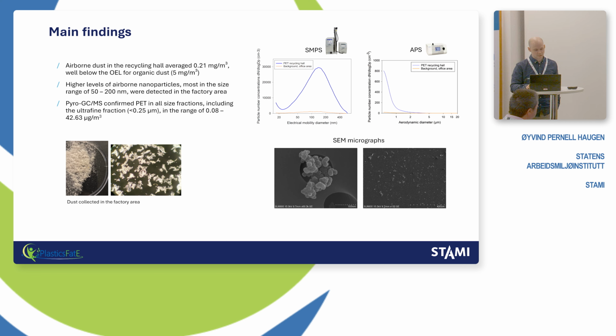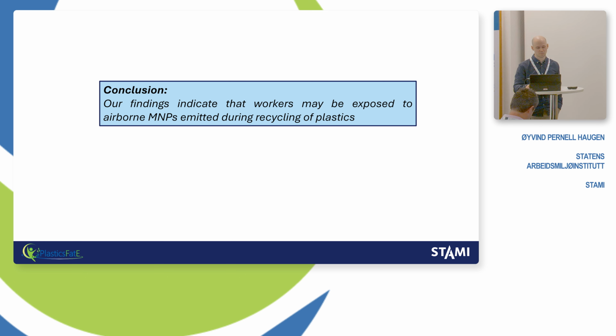And pyrolysis GCMS, I don't have the numbers, it's still being analyzed, but by looking at the raw data, we can see that we have PET plastic in the range of 0.08 to 43 microgram per cubic meter. And we have some scanning electron micrographs of what we believe to be plastics in this nano-sized range, and also dust that was collected inside the factory area, also looking like plastics. So the simple conclusion: our findings indicate that workers may be exposed to airborne micronanoplastics emitted during recycling of plastics.